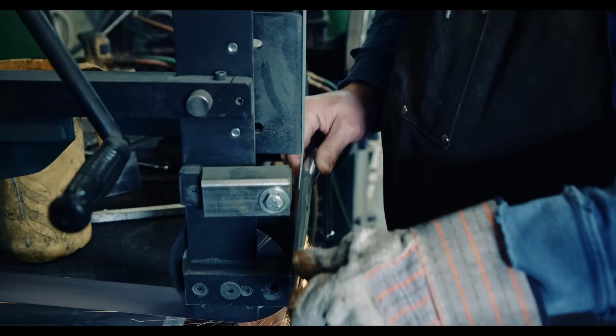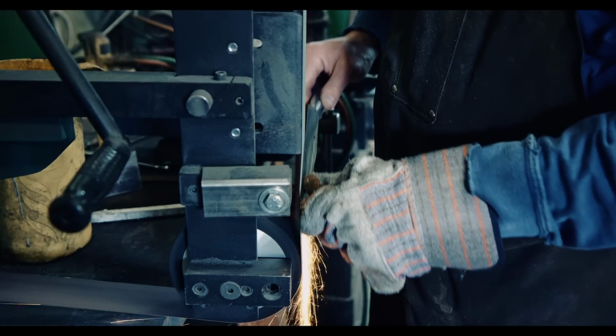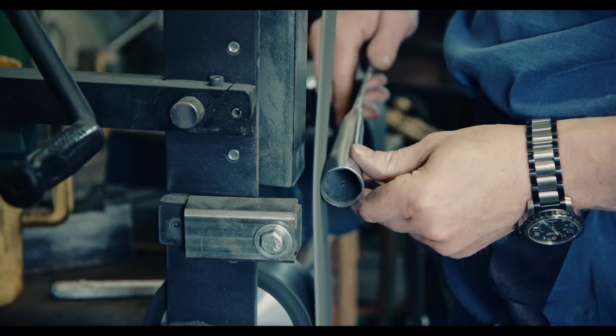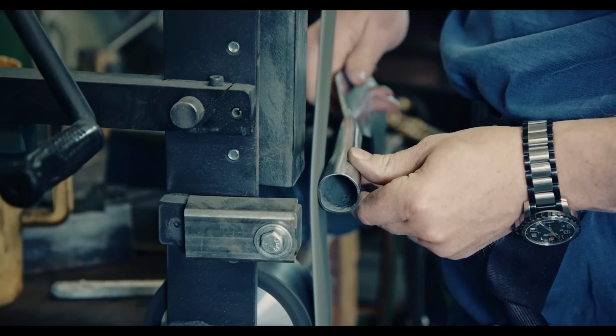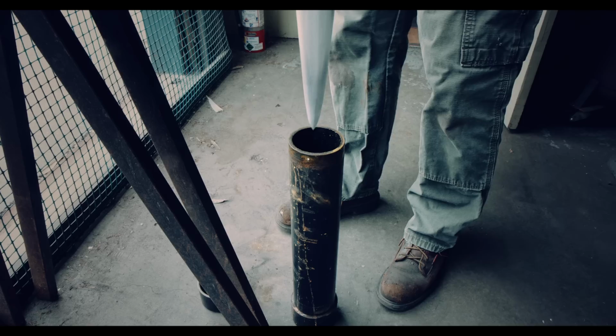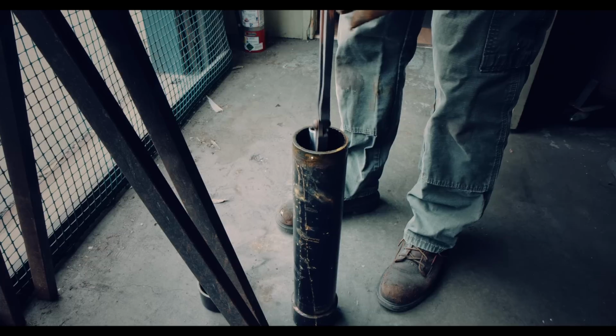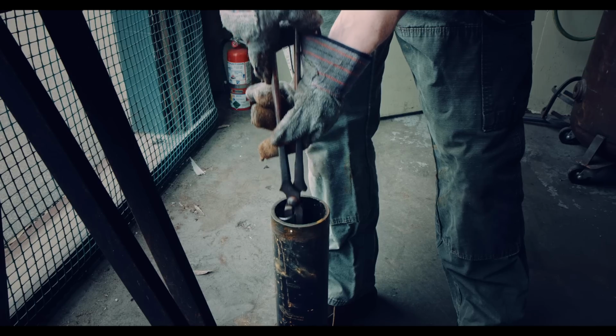Before I can place the spear in ferric chloride to bring out all the patterns, I need to clean it and remove any oils that might interfere with etching. I usually leave my blades in the ferric chloride solution for about 10 minutes, but let's just skip that wait.